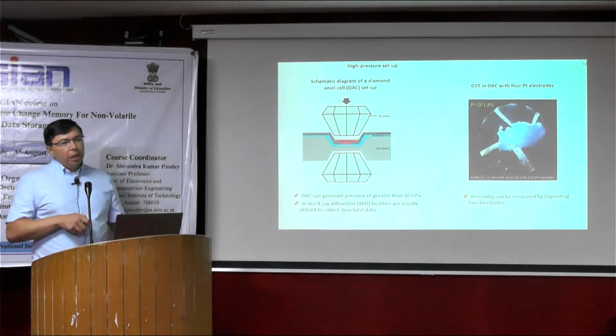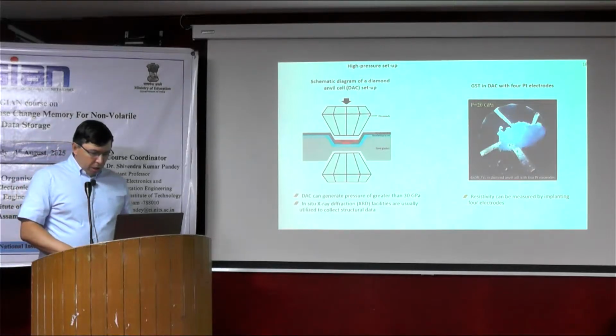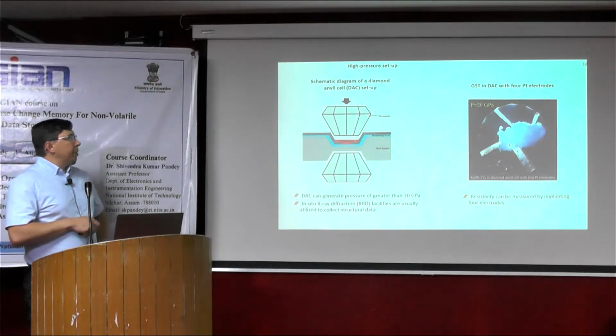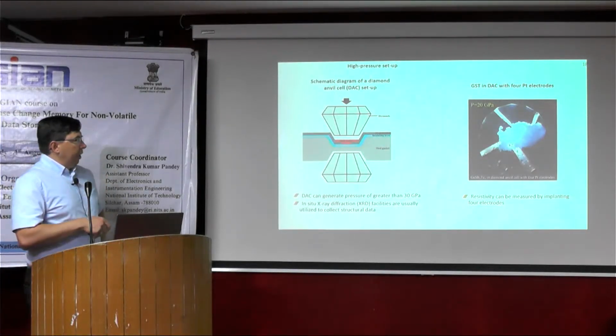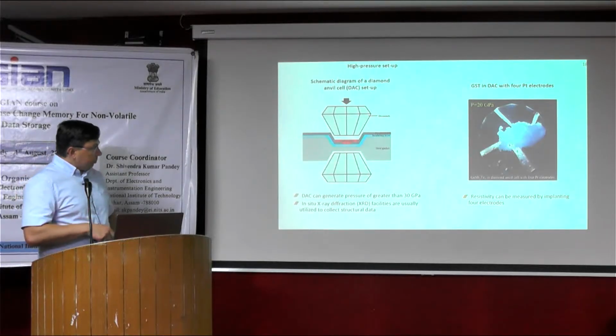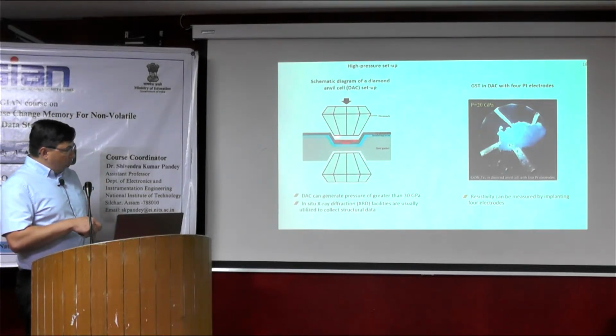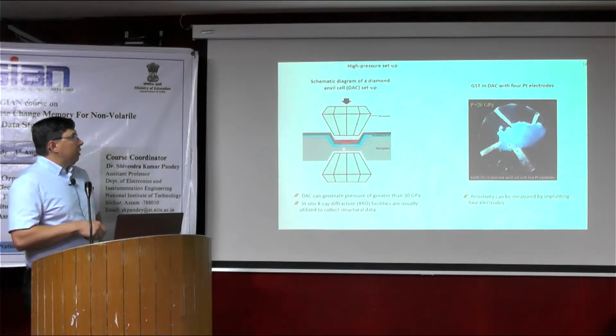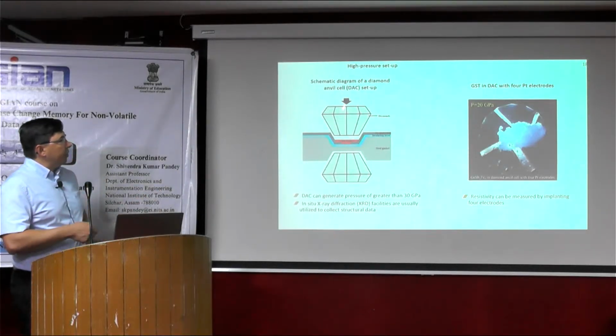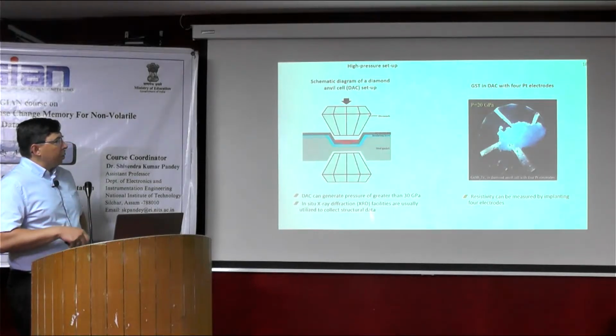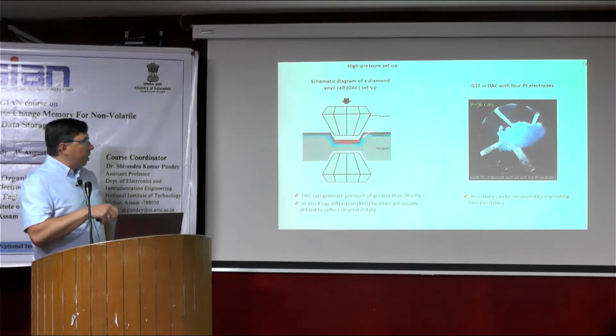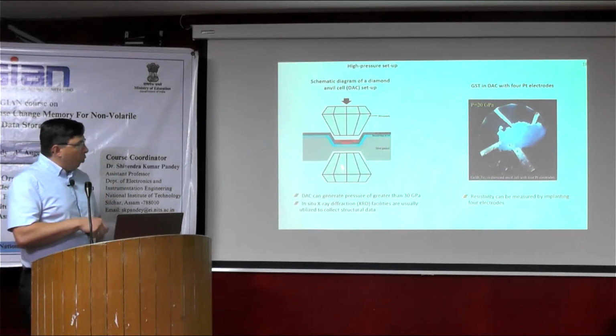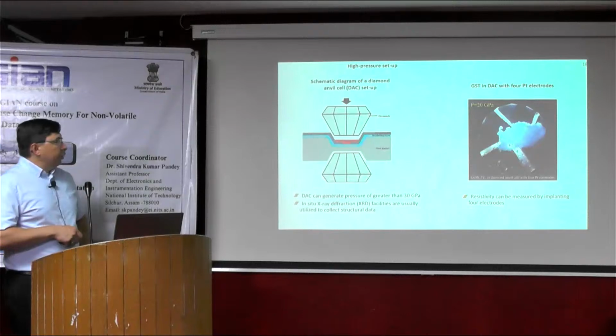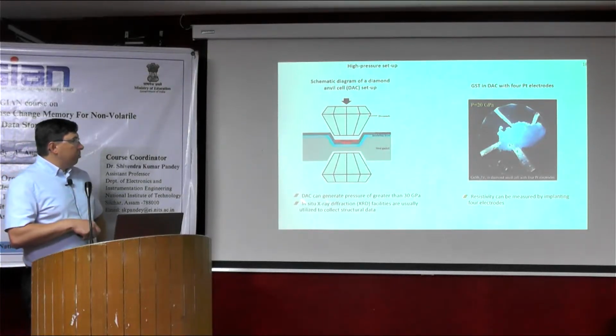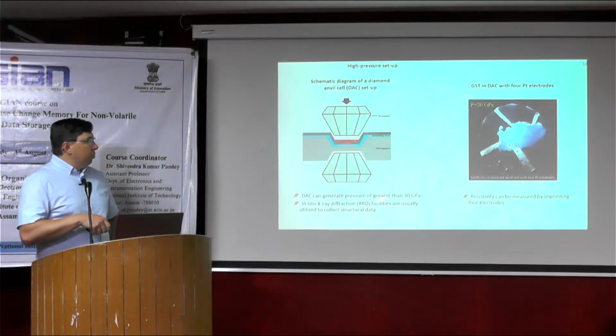How can we study this phase transformation? For this we need a special setup, and it's based on the diamond anvil cell, DAC, setup. Here this is the image. It shows two diamonds, and here this is the GST powder, and by moving and pressing these two diamonds, we can reach pressures of more than 30 gigapascal. And because the amount of our powder is not so large, we study this transformation using in situ X-ray diffraction, mainly by synchrotron.